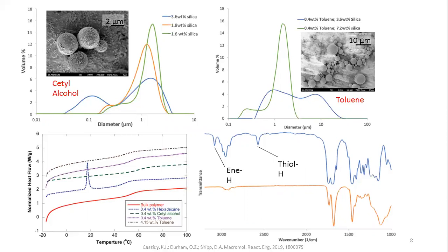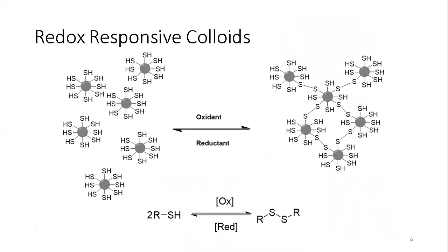We're not chemically incorporating them into the polymer, so they all should have the same Tg, other than the artifact of hexadecane, which has a significant phase separation with the monomer system, so you have the melt temperature of hexadecane in there. And you can see on the right, for ATR, we have near full conversion of thiol and ene, so successfully 100% conversion.